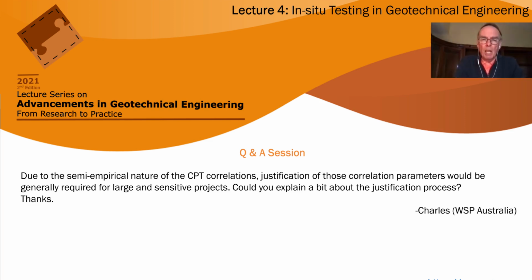deposit that's maybe millions of years old as opposed to less than 10,000 years, then it's got significant aging effects, and it's going to be stiffer than you would anticipate. You're still going to get a reasonable estimate of the peak strength because the cone is failing the soil, but your estimates of modulus will be off unless you measure shear wave velocity, of course, which is telling you it's much stiffer than you would expect.